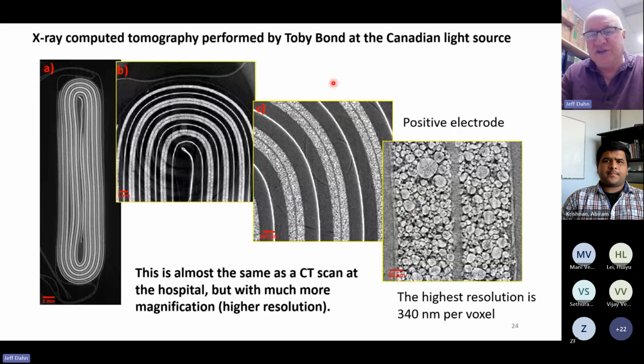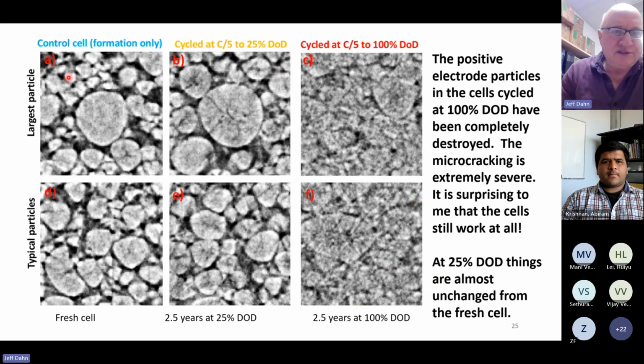So we wanted to take a look and see what was happening to these cells. So Toby Bond at the Canadian Light Source did X-ray CT on them after cycling for a very long time. And I'm going to show you some pictures at the highest magnification of 340 nanometers per voxel. So this is X-ray CT over on the left of the cell that's brand new. You can see the spherical NMC particles. And after 25% DOD cycling for 2.5 years, the particles look almost the same.